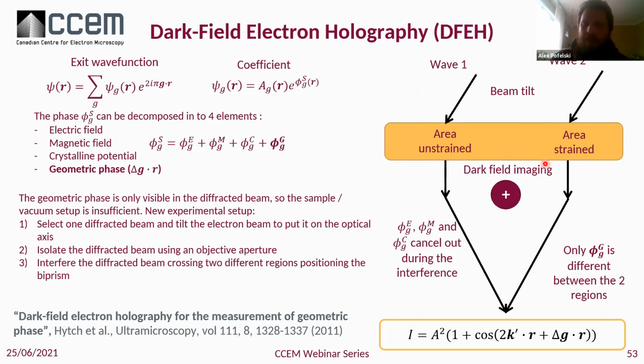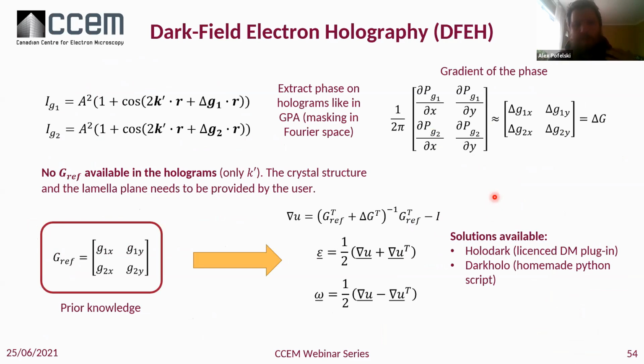So at the end, if you look at the interference between those two elements, all the other contributions to the phase cancel out, and you have only the delta G that is remaining in your hologram. So you can see that we are piling a little bit on this complexity. But at the end, if you just do two dark field holograms from two different diffracted beams, non-collinear, you can do exactly the same approach, extract the phase from the holograms like you've done in GPA, and you get your delta G matrix in the same manner as in the other techniques.